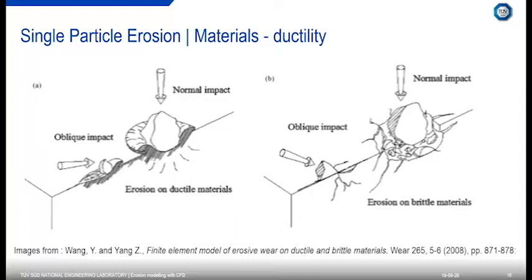So you can see that from the digging before it actually fails. So for example, we have ceramic materials are typically brittle and metal materials are ductile. So typically when we're looking at, say, a steel, we typically find that between about 20 to 50 degrees, so this is a ductile material, they'll dig and deform, where a brittle material typically experiences higher wear rates at angles close to about 90 degrees due to the fracture.